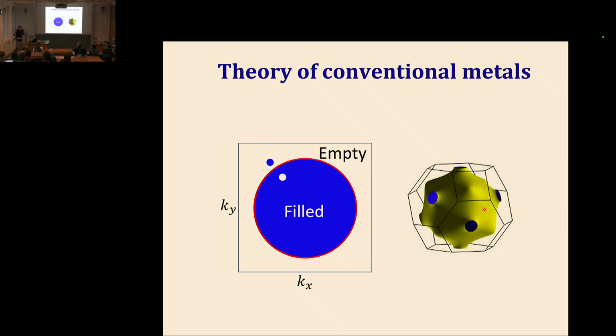You can calculate any low energy property of the system that you like. In particular, you can calculate transport, which is dominated by these low energy excitations. You can calculate magnetic susceptibility, specific heat, and so on. Just from this very simple picture, you don't necessarily know easily how to calculate the effective mass, for instance, or other effective properties of the low energy excitations, but you can fit these properties from experiments, and once you have that, you can calculate anything you want.